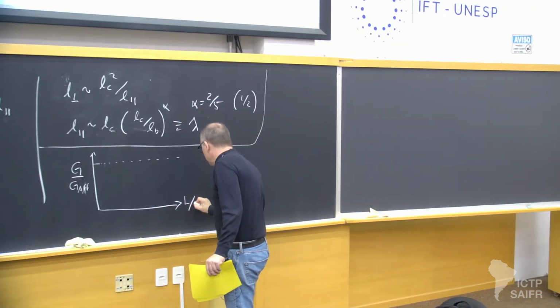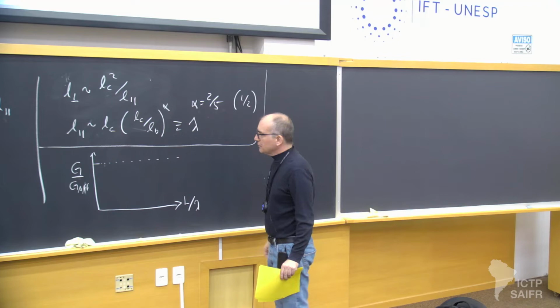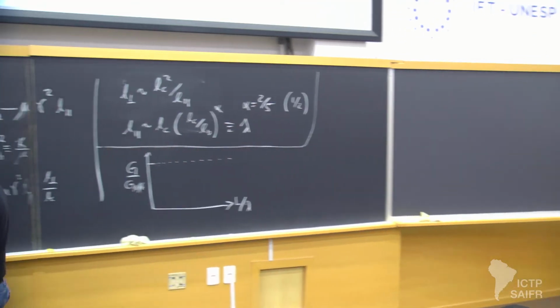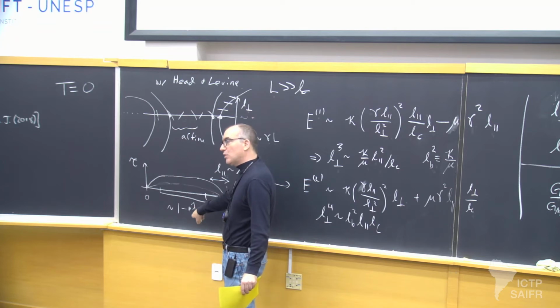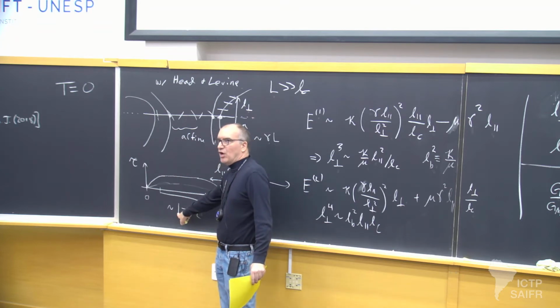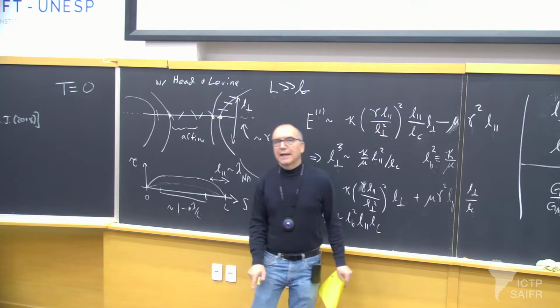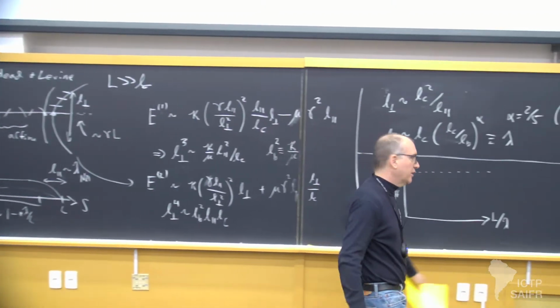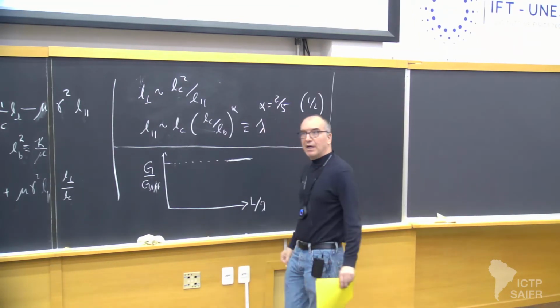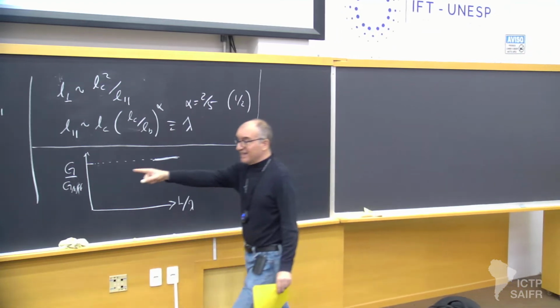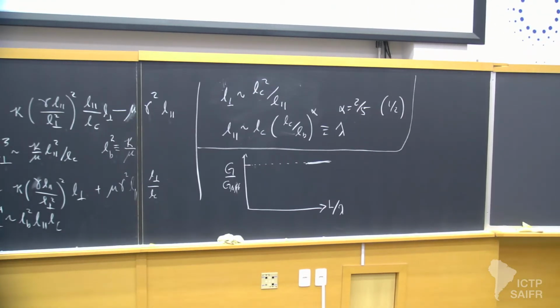If I plot this versus L over lambda, then as L goes to infinity, this ratio gets small. Basically, almost all the fibers are stretched, and stretched according to the macroscopic shear field. And so I should approach an affine behavior. Now that's again this much higher modulus, right? That's this thing. So I'm now saying that there's a network reason why this actually can be true, even though it looks like this should be much softer.